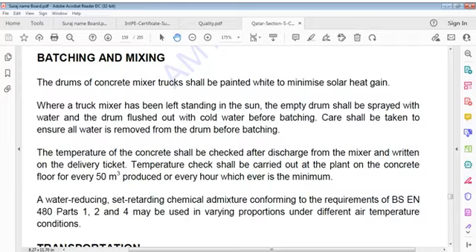Temperature of concrete shall be checked after discharge from mixer and written on delivery ticket. Temperature check shall be carried out at plant on concrete for every 50 cubic meters produced or every hour, whichever is minimum.